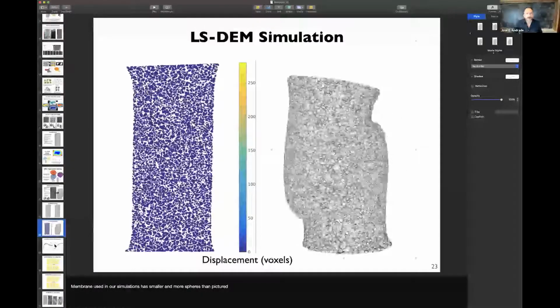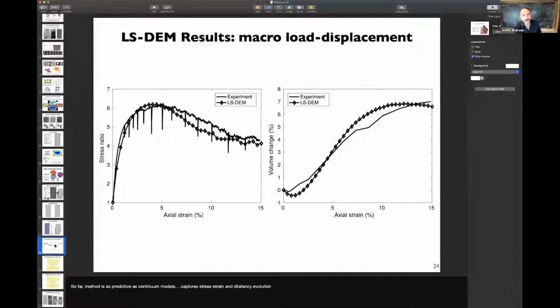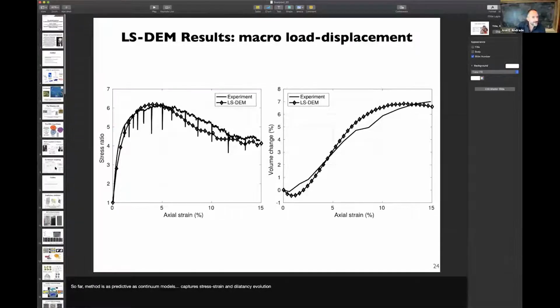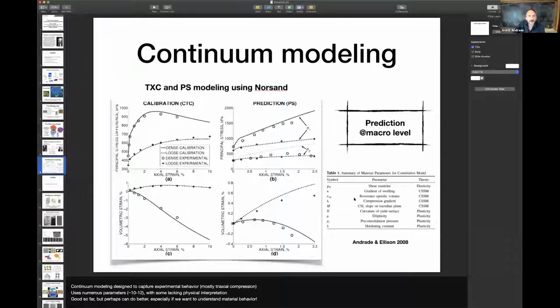Okay, but now let's start to make some comparisons with the data. So here is how the model compares with the macroscopic response of experiments. So this is what your good old constitutive model would attempt to do, right? You would try to match the stress strain curves and these dilatancy curves. And if you could do it with a suitable set of parameters, like the ones I showed you over here, in my constitutive model of Nor-Sand, you would declare victory.